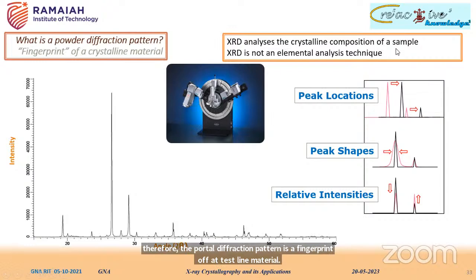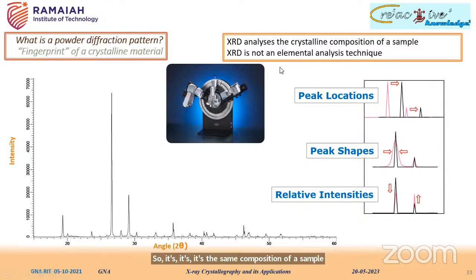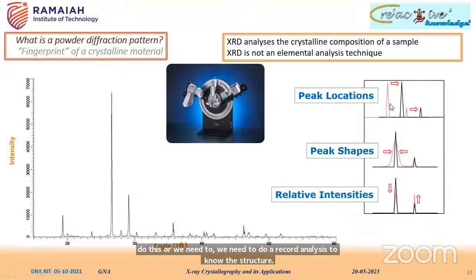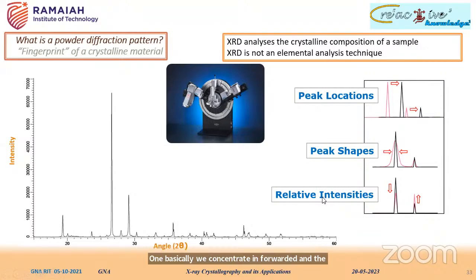XRD analyzes the crystalline composition of a sample, and it is not an elemental technique. So you cannot just judge from these peaks which element is present and what the composition is. Further, we need some complementary technique to do this, or we need to do a Rietveld analysis to get the structure information. What we basically concentrate on in powder diffraction is peak location, peak shape, and relative intensities. This information gives complete information about the atomic arrangement, as well as the phase, and even the quantity. So quantitatively and qualitatively, we can identify the composition.